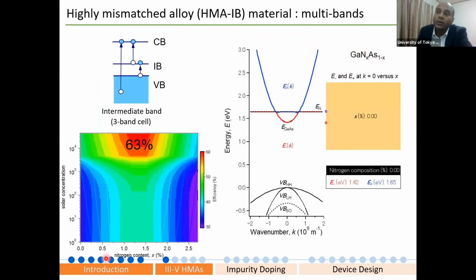So right here, one of the world record technologies for the multi-junction solar cell uses gallium nitride arsenide for the 4-junction solar cell. But here I show what exactly happens in gallium arsenide if you have nitrogen doping. For example, you know gallium arsenide's conduction band has this kind of dispersion, and the valence band has heavy hole, light hole, and spin orbit bands. But if you have a very tiny, dilute amount of nitrogen impurity, the impurity state is right here.